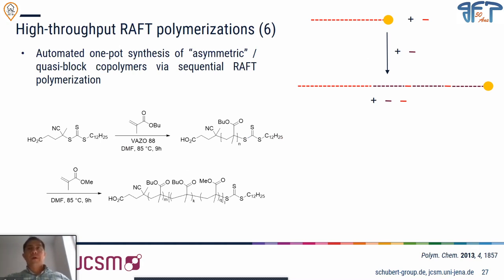But moving on, I was also very interested at that time in building block polymers, let's say in a fast way or in a lazy way. Via RAFT, once you want to build up a block polymer, first you start with the first block, you bring it to, let's say, 60, 70, perhaps 80% conversion to avoid that many chains are dead.